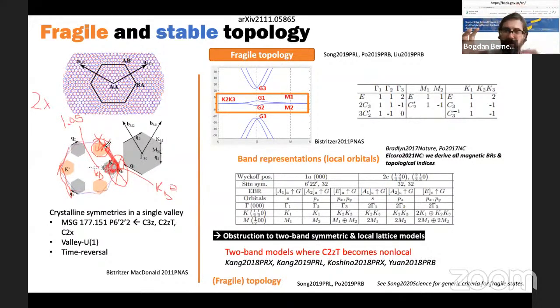To make them couple, I would have to basically do perturbation theory and tile them across a wave vector of order KD. Okay, but these Brillouin zones are KD times theta, so I would have a perturbation theory in T between the layers, so T perpendicular over T parallel to the power 1 over theta, which is the number of times I have to tile them from one K point to the other K point of the original graphene lattice. This perturbation theory is, of course, exponentially small as the angle gets smaller.